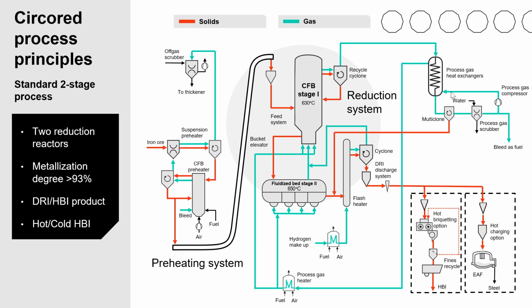At the upper right, we have a section dealing with the gas treatment, first recuperating heat from the process off gas via a heat exchanger and then removing dust via a multiclone. The dusty material is then blended with the product stream to minimize production losses. The remaining dust and product water get removed by a scrubber system. The hydrogen gas gets then recycled back into the process. The hydrogen bleed is used as fuel for heating purposes.